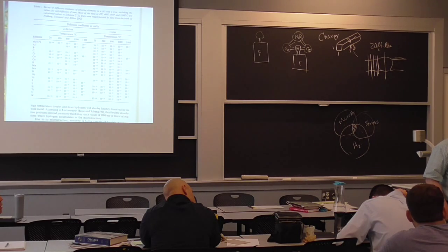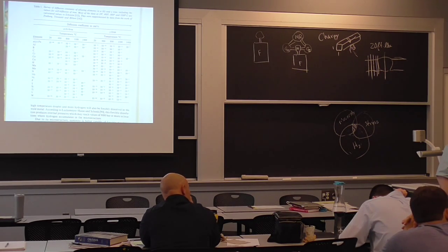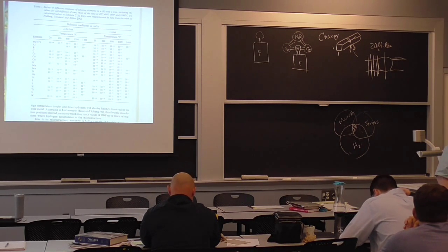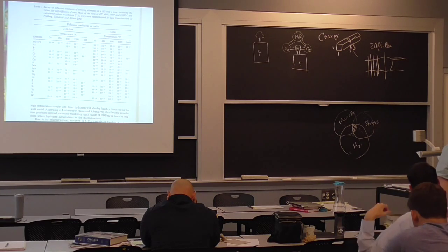So we don't do that because it's cost prohibitive, I'm assuming? Well, yeah, it's sort of a scientific curiosity. It proves the point that if you're ultra clean, you can't make steel that clean on a tonnage basis. Maybe 100 years from now we'll have some way to do it, but today we make steel that's 30 times cleaner than it was 50 years ago. That's why we don't have lamellar tearing. That's why we don't have hot cracking. Not hot cracking, but reheat cracking, when you put it in a stress relief furnace and things go to the grain boundaries. But we still can't make perfect materials.